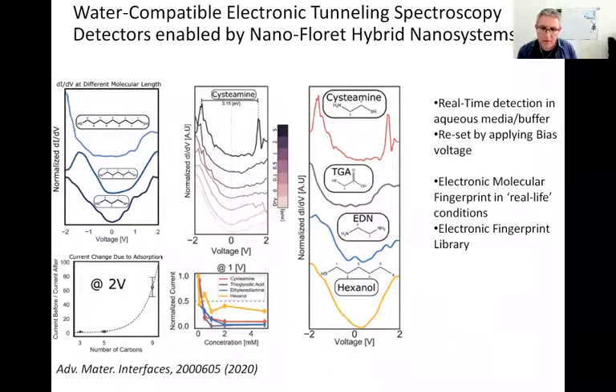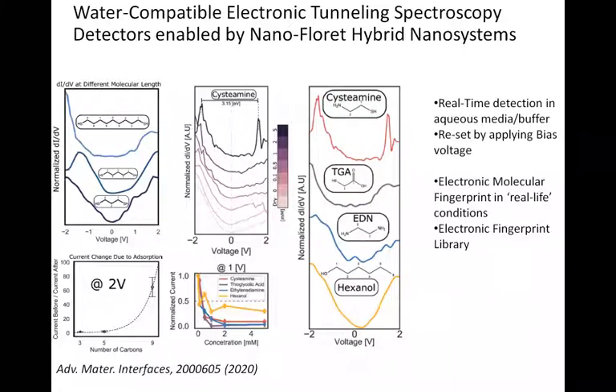Okay. Yeah, so this is electron transfer mediated by the molecular assembly at the interface. We have results that we have not published yet, where we also can demonstrate mediation by proton transfer. So basically you have a platform that is sensitive to electron and any charge carrier transport at the interface across monolayers. And the details really depend on what you put in the interface.